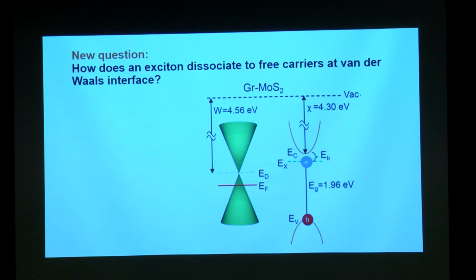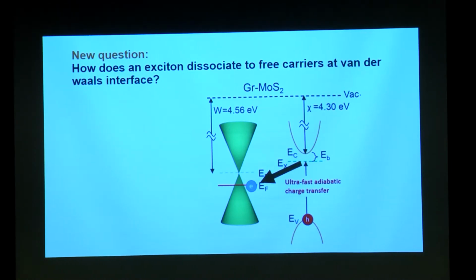When I shine light, I have electron and hole formation. This is where the electron goes, and this is where the hole is. The moment they form, the electron finds this energy of graphene to be a lower energy state, so it jumps out and goes here, giving an ultrafast adiabatic charge transfer. That's what we guess should happen, and this is what happens in conventional semiconductor-based van der Waals heterostructures.